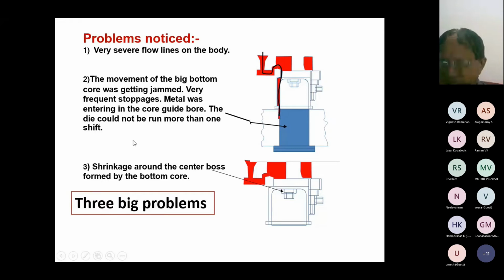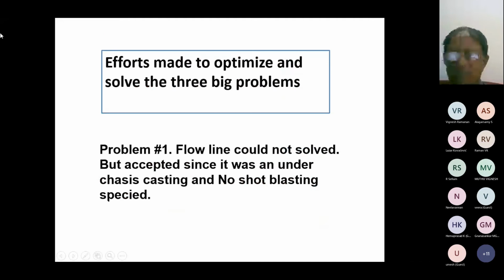How to do that one? This I also had. No, shot blasting is not required. That is, we are able to get away with the flow lines. Though the flow lines were severe, after shot blasting, these flow lines will sometimes show up some surface defects. But we are lucky. No shot blasting was asked by the customer in this casting. So with the severe flow lines also, we are able to get away.